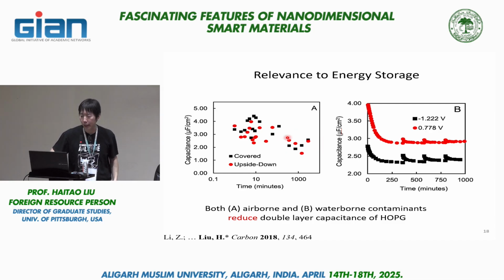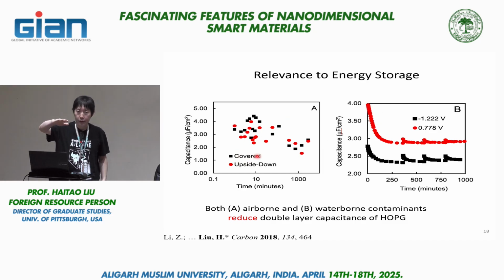Okay, but regardless, we see this reduction on the basal plane of graphite, and we see this whether the surface of the graphite is on top, face up or face down. It doesn't matter. So in this data set, it seems to suggest that it's not particle contamination, but rather molecular contamination.